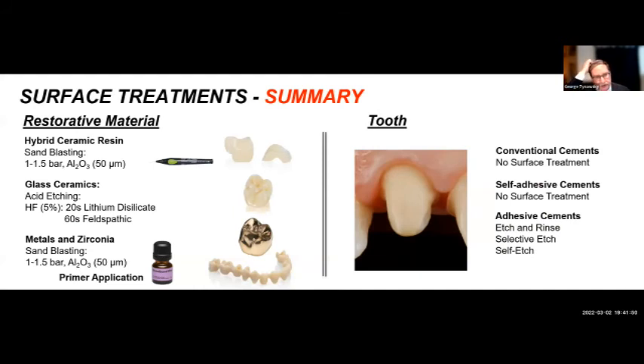So first, we're going to look at the restorative materials and the surface treatments, and then we'll look at the tooth. On the restorative side, we could have a composite-based crown, like a Lava Ultimate or Enamic. Basically, it's a hard to roughen material, so you create a micromechanical retention through sandblasting. The glass ceramic materials like feldspathic porcelain, lithium disilicate and leucite reinforced require hydrofluoric etching. The hydrofluoric etching, in the laboratory or chairside, creates a micromechanical retentive pattern for the restoration. And for the zirconia, we lightly air abrade it and we use a chemical primer called a metal zirconia primer. There are a number of them. Ours is Monobond Plus, and there are others from Kerr and Bisco that have multifaceted chemistry where they're primers and create MDP bonds with the crystal structure of the zirconia and the metal oxides as well, to provide a very strong bond in these restorations.